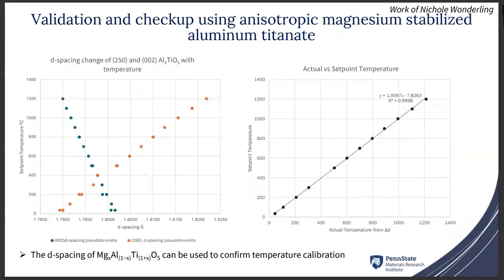In order to validate these results, which is very important, this is work that Nichole did with another laboratory. They use a magnesium stabilized aluminum titanate material that has a specific d-spacing change between the 250 and 002 diffraction pattern, and this change across temperature can be compared across labs.